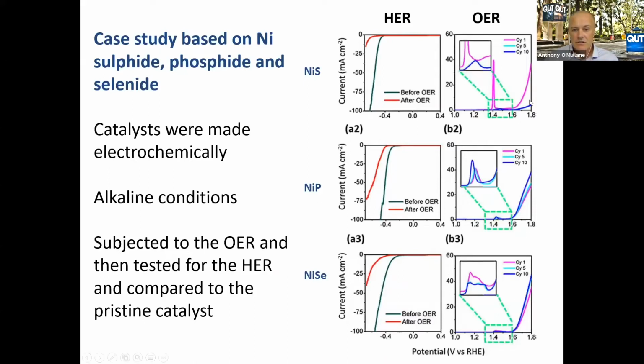We can see the oxygen evolution reaction for the phosphide and the selenide actually improves with the number of cycles, whereas there's a dramatic decrease in the hydrogen evolution reaction after you do oxygen evolution. So you're getting a real compromise in activity if you allow your cathode to be oxidized in any way. If this was plugged directly into a solar cell, when the sun doesn't shine anymore and your electrolyzer turns off, you're into that reverse current regime, which would then be detrimental to your cathode.